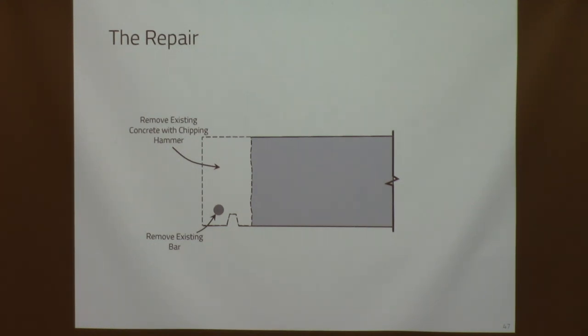we heard all kinds of things, and I can tell you at the end, during the litigation stage, people were saying, oh, just go in there and put some FRP sheets over the edge of it, you'll be fine. Well, that's, in my profession in repair, a no-no. You don't hide corrosion issues. You've got to address the corrosion issues. You can't go in and put something that's just basically going to be a catcher for any corrosion. You've got to deal with the corrosion issue, then you can do other things. So the only way to really deal with it is to take out the offending bar, removing that concrete from the exterior. And when we're doing that, of course, we've got to worry about the post-tension anchorages that are right near that end. So it can be a dangerous business, but we've done it enough times.